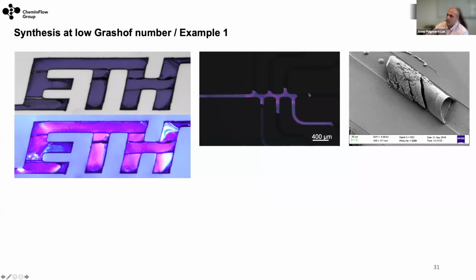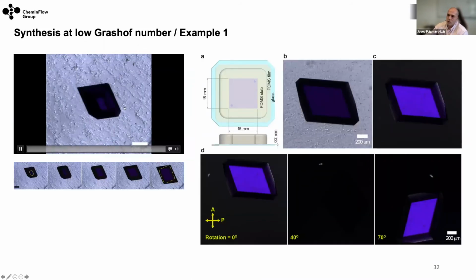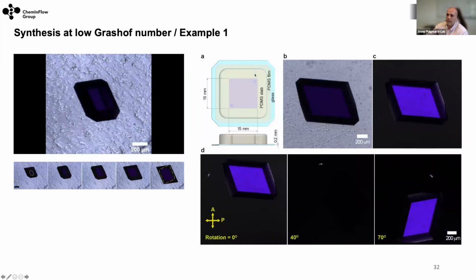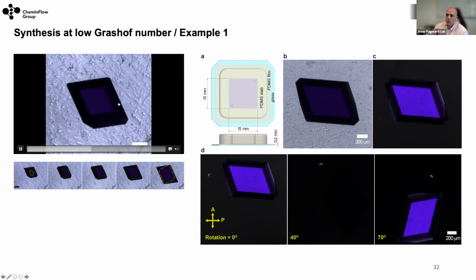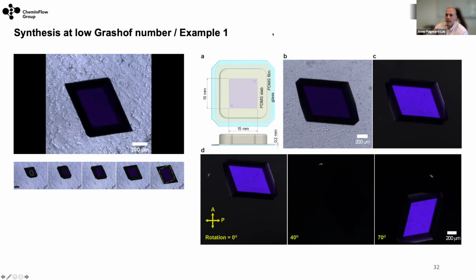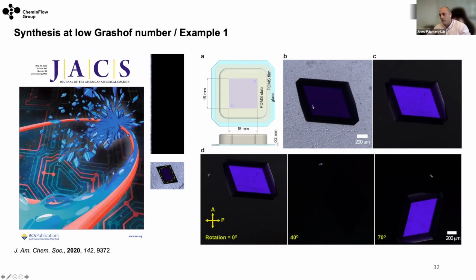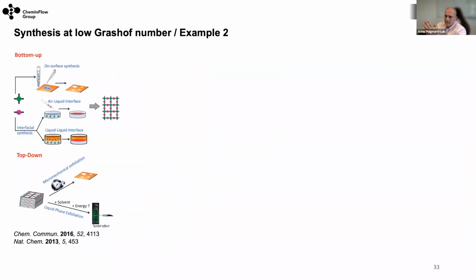As you see, normally these crystals have a polyhedral shape, but in that case, you see that they have this semicircle shape. But we can also do flat crystals. So if we change the microfluidic device, what we can grow is a kind of film with the same chiral morphology. So yeah, it's also a single crystal. We were lucky to get the cover of the journal here too. But this is something that we developed later.